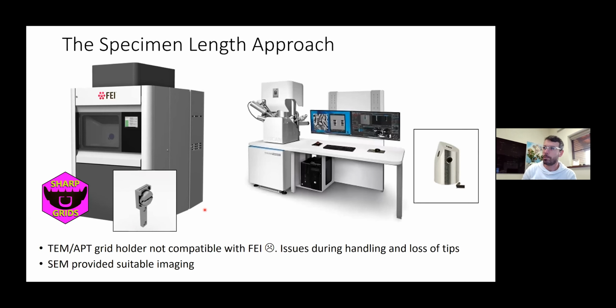What we've done then is we just used an SEM. So this is a Tescan Clara that we have at Curtin, one of the latest generation, which provided some really good results. In there, we used a pre-tilted specimen holder in order to get the atom probe specimen normal to the beam.